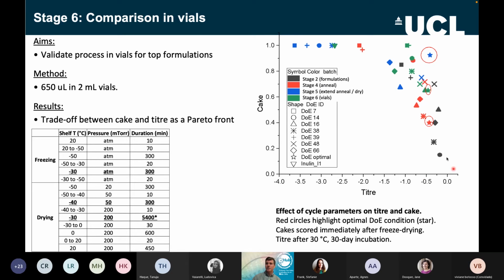And what you can see here is a distillation of everything with the current process. This is the titer performance for any given formulation against its cake performance, and you can clearly see the microplate results in blue, red, and black from those first stages 2, 4, and 5, where we started annealing and extending it, overlaid with the vial performance in green. So you can see that trade-off. It's like a Pareto front trade-off between the two. But you can see now the vials are hanging out in this top corner here, which showed us that whilst not exactly performing the same way as the microtiter plate data, they were generally better in terms of the Pareto front, at least, maybe not on an individual axis. So that turned out to be really quite encouraging, that we could switch to vials quite happily.